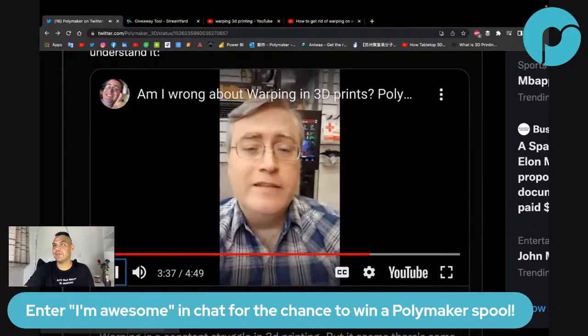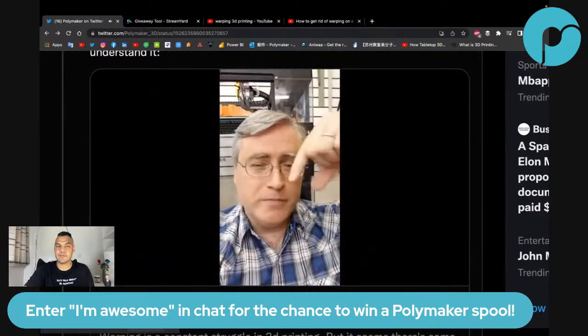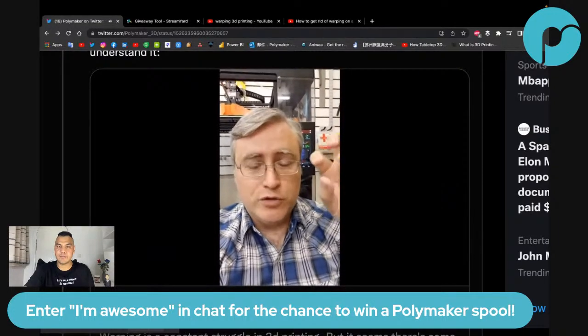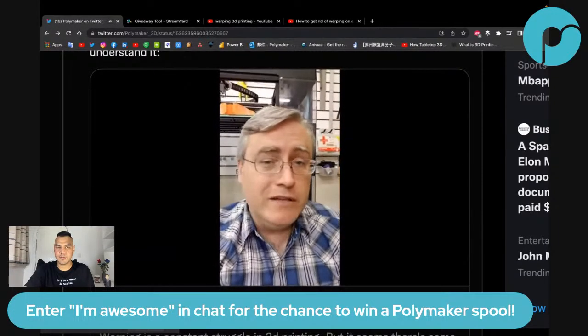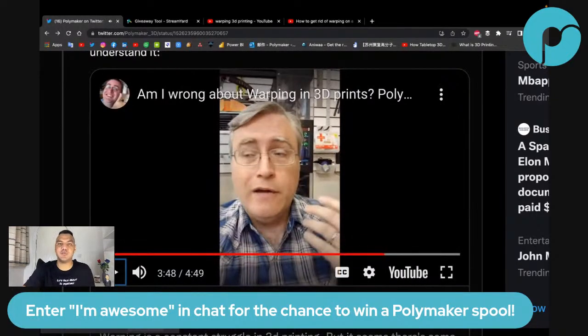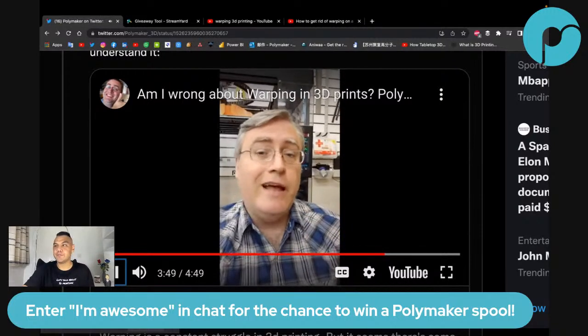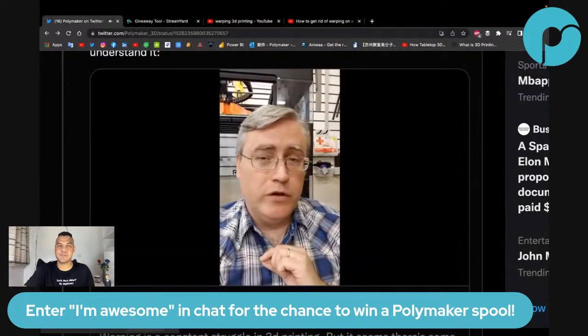To test this, take a 3D print with long, thin parts, because those long, thin parts are more likely to shrink, and print them in thicker and thinner layers and see if you get different warping with it. Yes, that's very straightforward. Actually, there's a video on YouTube that he shared with me where someone was printing with small layer height, and he got very small warping, and with bigger layer height, he had more warping. So from that video and from his explanation, it makes sense. You get what I mean? And from my explanation, I was going to say that you will have to understand the background, but I was going to say that bigger layers will help. But that video proved me wrong. I've tried it. I get more warping with thicker layers and less warping with thinner layers.